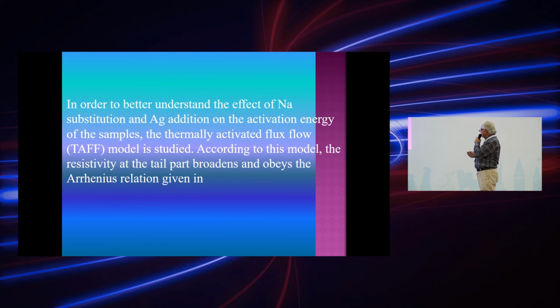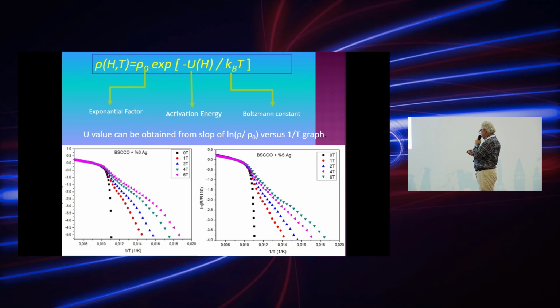In order to better understand the effect of sodium substitution together with silver addition on the activation energy, we used the thermally activated flux flow model. According to this model, the tail part of the transition obeys the Arrhenius law, and the Arrhenius law is given with this formula here. Rho zero is the exponential factor, U is the activation energy or flux pinning energy, and kB is the Boltzmann constant. The U value can be obtained from the tail part of these figures by plotting the logarithm of resistivity versus 1 over T, and the slope gives the U value.